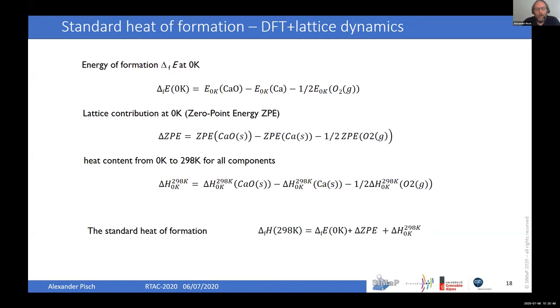And so if we sum up everything together, then we can get the Gibbs energy. And so first of all, the heat of formation, we calculate it at 0 K, and I give an example here for lime. At 0 K, we have CaO minus the energy at 0 K for calcium minus half the energy of oxygen gas. And so this gives me the energy of formation at 0 K.